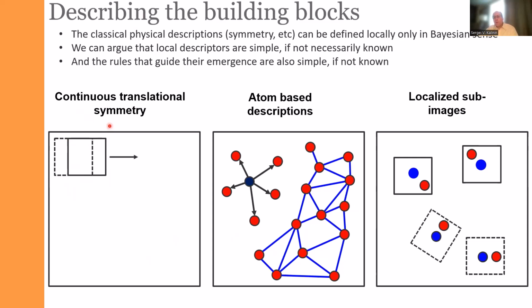So if we work with the data, sometimes we can make descriptors based on some objects of interest. For an atomically resolved image, the natural object of interest is the atoms, so you can find their positions. For mesoscopic resolution images, we can use techniques like SIFT, scale invariant feature transform, blob finders, edge finders, whatever. But the choice of your feature finder determines what you are going to learn from your analysis.